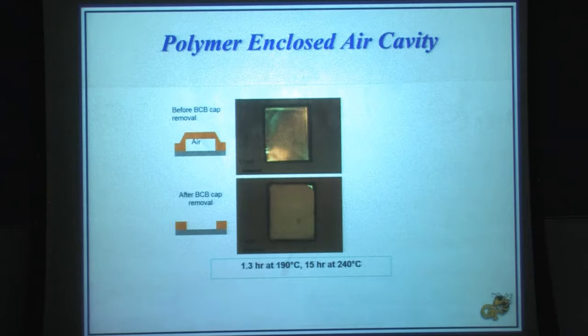These are rather large cavities — here's a one-millimeter marker bar. These were rectangles of about 2 × 3 mm and pretty good thickness. Looking through the transparent BCB overcoat at the silicon surface, you see a very slight blemish on the silicon — when you peel the overcoat off the blemish is still on the silicon, so the silicon is quite clean, with only an ever-so-tiny residue left from the decomposing polymer. You can also see a slight wrinkle in the BCB of no real consequence.